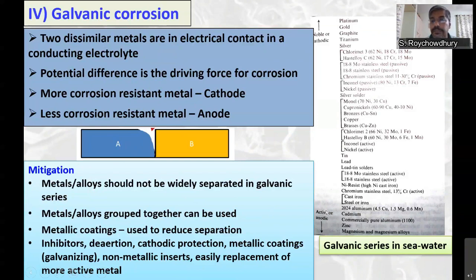Metallic coatings are used to reduce separation. If you cannot avoid electrical contact between two largely separated metals, then you use a coating or a film in between, which is intermediate in this galvanic series, so that the gap reduces. Use of inhibitors and deaeration will reduce the corrosivity of the environment. Cathodic protection will help so that both these metals become cathode and they will not corrode. Metallic coatings like galvanizing, the zinc coating of iron, also help in minimizing galvanic corrosion because zinc acts as a sacrificial anode and the base iron is protected.